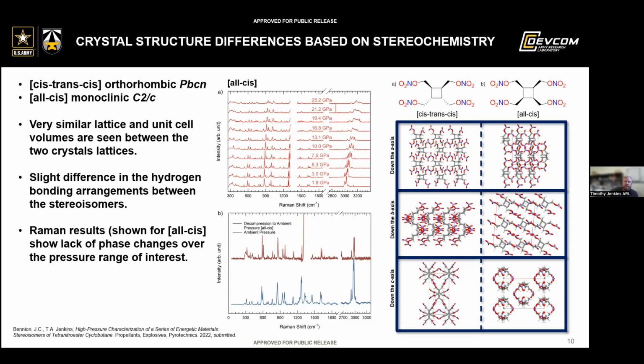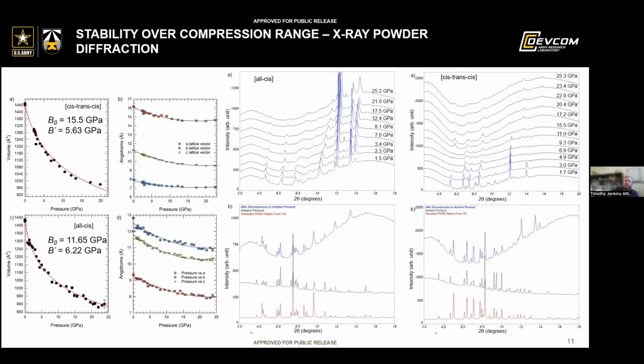So because everything is sort of the same, we can then look at the compression over this pressure range with the X-ray diffraction, and you can see basically the same sort of trends between these two materials with a couple of slight differences. And I want to highlight those on this slide. First of all, you notice that there is a different bulk modulus between the two, and you can see that there is a slightly different volume change associated with the cis-trans-cis and the all-cis structures.